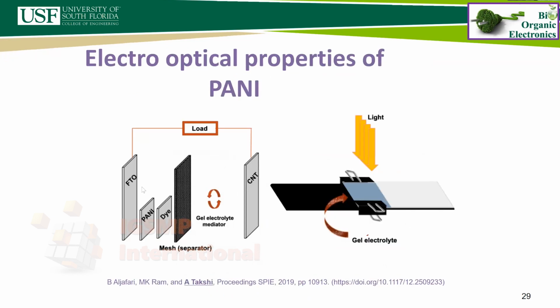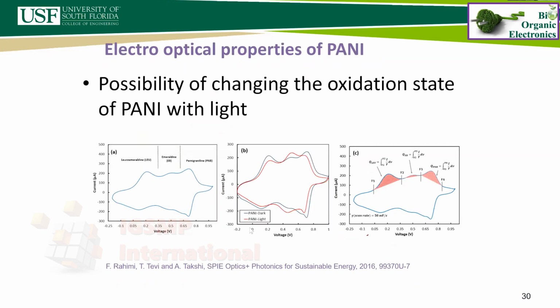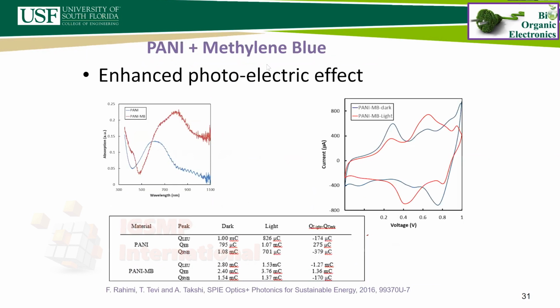So applying that in the same sort of design, making the cell with the polyaniline dye and carbon nanotube counter electrode, we saw that in the liquid electrolyte, we can change the oxidation state of the polymer just by shining the light. And when we have a good dye like methylene blue, the amount of harvested energy translated to electrical energy would be significantly higher. And all that leads us to a good point.